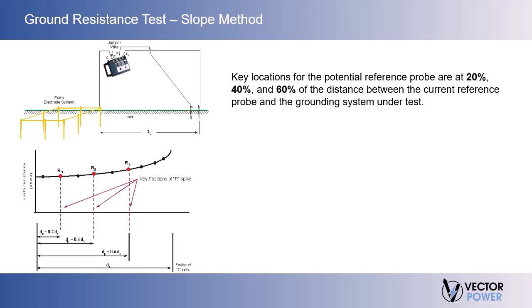Once the curve is drawn, we need to calculate the slope coefficient, mu. To do this, we take the resistance value recorded at our key potential reference probe locations, and we call them R1, R2, and R3 respectively. To calculate the slope coefficient, we use the formula R sub 3 minus R sub 2 divided by R sub 2 minus R sub 1. This will provide us a measure of the change of slope of the ground resistive curve.